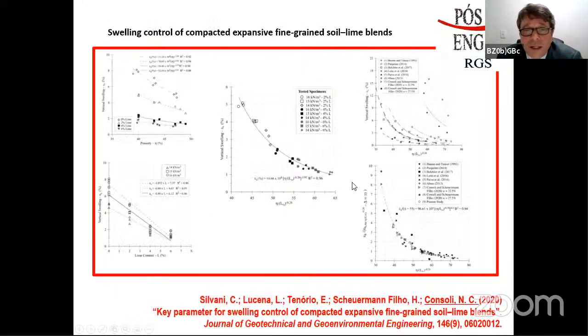In this case here, we have treated one soil that was expansive with lime, and we have shown here different amounts of lime, different densities that we have had. You have a unique result based on porosity, lime content, and then we have the vertical swelling of it. We have tested, getting from the literature from other authors, results that people have had, and then we have shown that it controls completely.